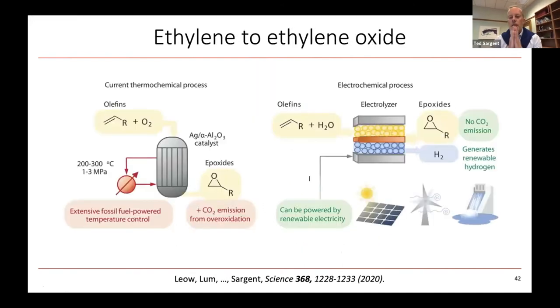And so we also recently asked the question, could we produce electrocatalysis on the anodic side in some kind of systems approach where we could get into the amp range? What we found in the previous work and in other attempts was that when we tried to go to higher potentials and higher current densities, typically we really lost the selectivity, which is absolutely critical to these processes.